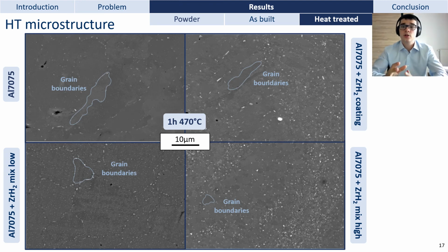On this micrograph, for each alloy, the network of precipitates delimiting the grains was globularized by the solution heat treatment. Moreover, the small globular precipitates inside the grains are less visible. We can also see the grain boundaries as highlighted on the pictures. The proportion of second phase is more important for the plasma-coated and the high zirconium content mix than for the two others, since there was a higher density of grain boundaries for these two alloys. All these precipitates still need to be identified precisely with TEM analysis.